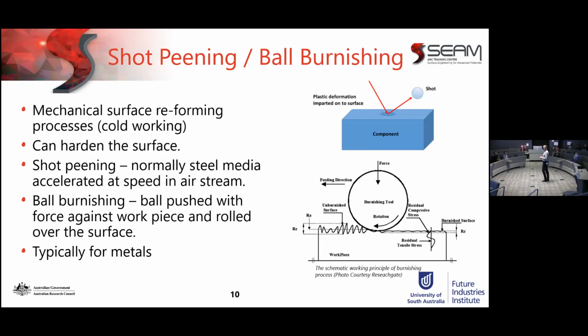Shot peening, ball burnishing. I saw Mohammed here, this is for you, Mohammed, he does some research on ball burnishing. They've got a PhD student doing combined shot peening and ball burnishing surface improvement. These are going to improve surface finish. Shot peening will definitely harden the surface and get an improvement in surface roughness, but maybe not enough. Ball burnishing, that's a technique where you're rolling the ball under force across your path, plastically working that surface, and that will end up smoothing and also hardening at the same time. Both of these processes are only going to be useful for metals.